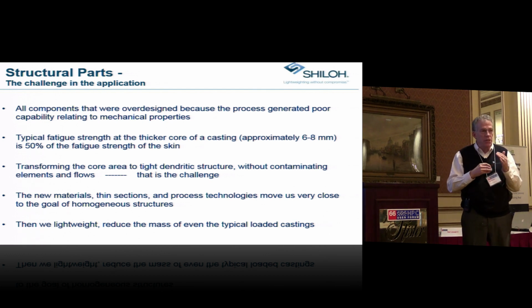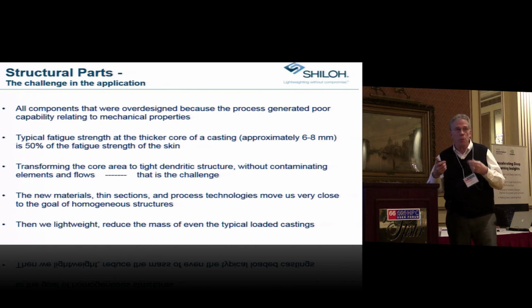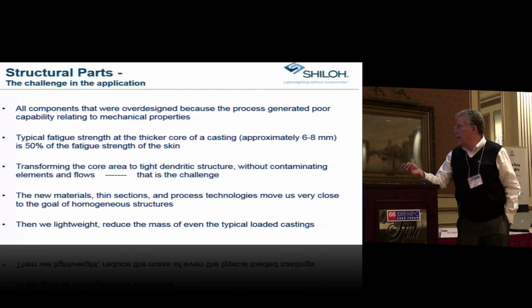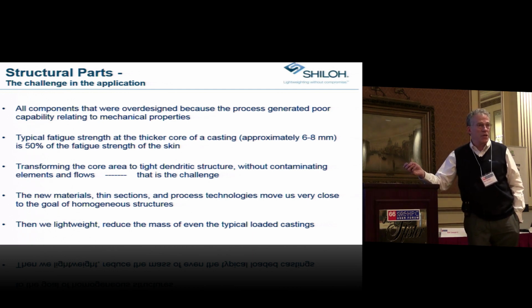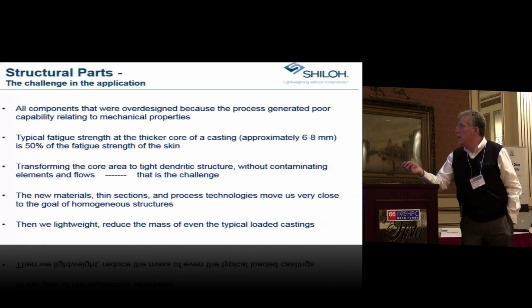So the only way to reduce the over-design is to really have a continuous homogeneous structure on the inside of a casting wall, which is solidifying. It has to solidify quickly, it has to solidify the same way, and it has to be free of gas. And those were all problems that were part of the high-pressure die-cast solutions. So we do all that right, and then we lightweight by reducing the mass of those typically loaded castings through the design and what we can do with our design areas. So this is kind of the challenge.